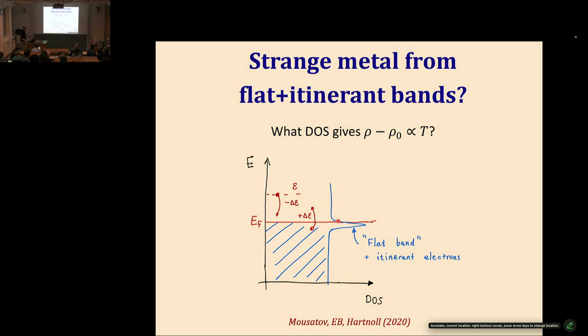Okay, so there's a lot of entropy coming from this flat band. So this has to be removed at some temperature. This cannot really be a theory for linear T resistivity that extends all the way to T equals 0. Which doesn't mean that it can't explain some crossover regime which looks linear down to quite low temperature if this band happens to be flat enough.